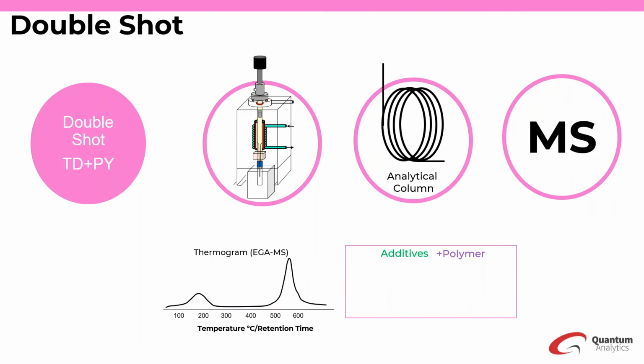Double shot combines both of these techniques. The sample cup is dropped into the furnace. It's thermally sampled to extract out any additives. The cup is dropped back into a heated furnace this time to be flash pyrolyzed. You get at the end two pyrograms or chromatograms of your pyrolysates. So the pyrogram of your polymer is truer to the polymer backbone of your sample because you thermally desorbed out all of those additives and your lower molecular weight compounds.